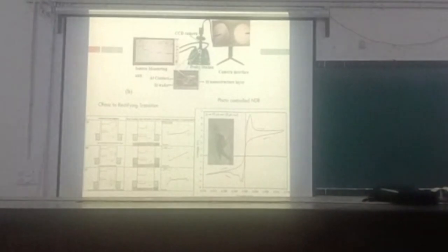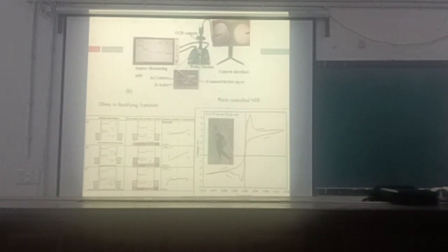So thin layer means tunneling takes place. So that tunneling gives rise to this kind of oscillations. And when we focus on the average nanocrystal material, we have got two very nice results. One is by controlling the surface state density, you can make your device from non-ohmic to ohmic to rectifier.